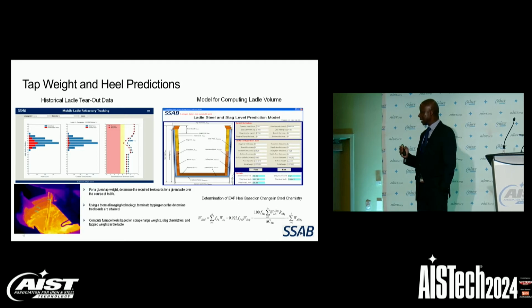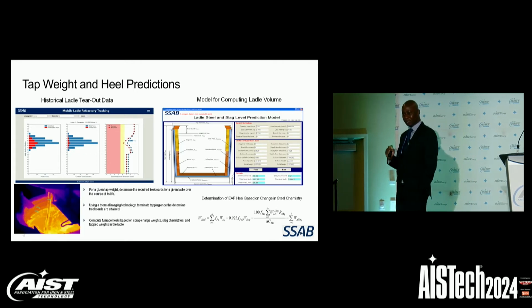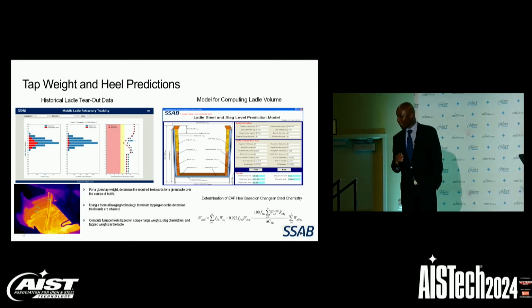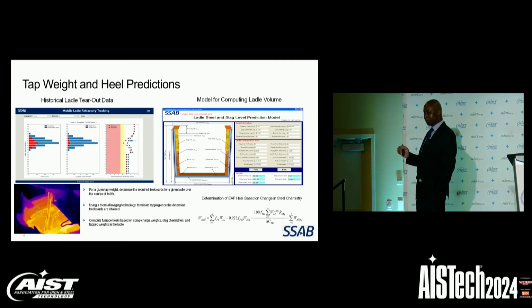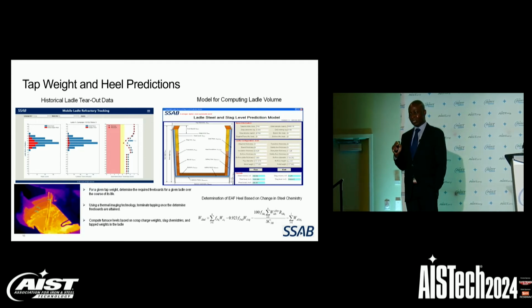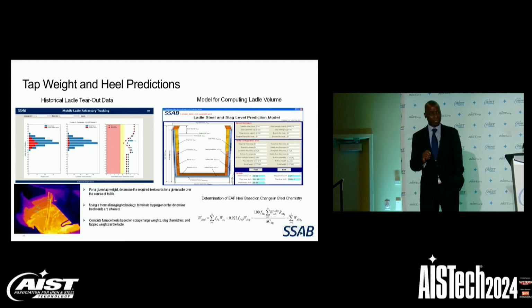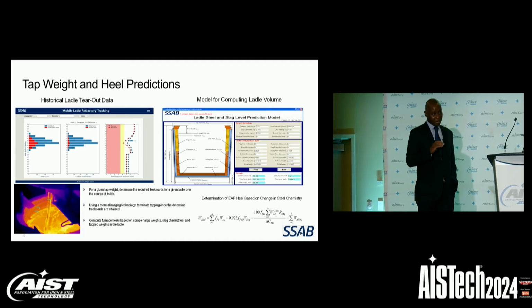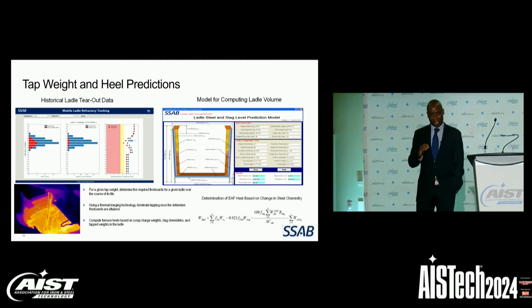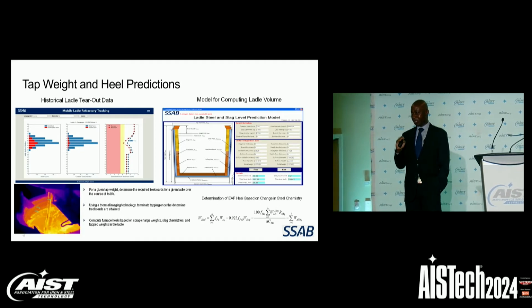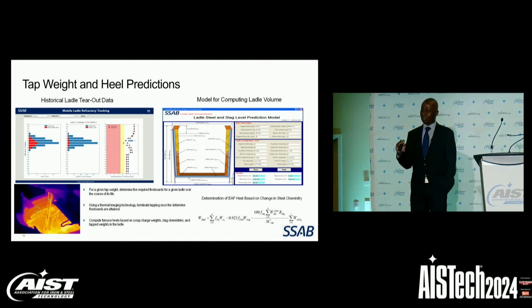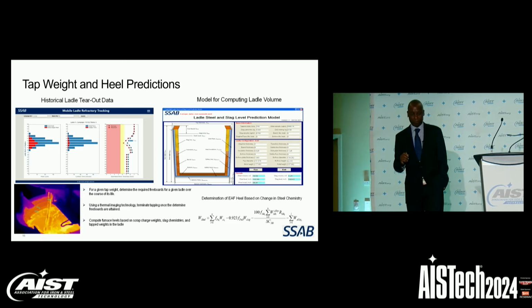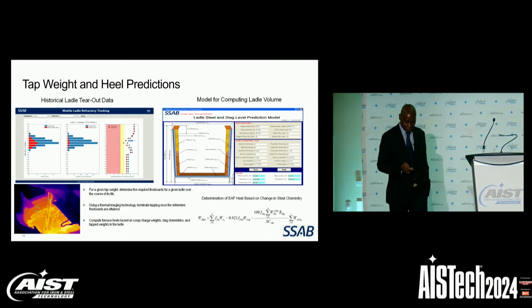So when a ladle is designated for tapping and a tap weight is specified, our model determines the freeboard in the ladle. And then you can now use a thermal imager to monitor the temperature of the refractory in the freeboard region. And then as the level of the steel is rising and when it contacts the freeboard region, the change in temperature can be used to terminate tapping, leading to consistent heel control during scrap melting in the furnace.